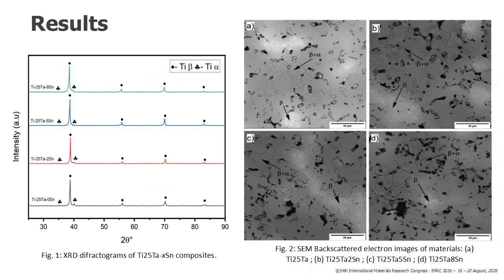The results of X-ray diffraction analysis show that the titanium alpha and titanium beta phases are present in the titanium 25 tantalum tin alloys. With the addition of tin, the intensity of the main peaks of the alpha phase gradually decreased. This indicates that the addition of tin allowed a higher proportion of the beta phase to be retained during the cooling. Furthermore, no notable tin diffraction peaks were detected in the patterns.